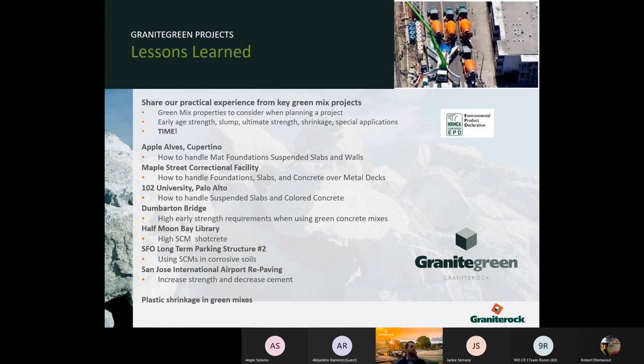Another one similar to the Dumbarton Bridge is the SFO long-term parking structure. The engineer had a very conservative spec, meaning more strength required than really needed. However, they also wanted to incorporate SCMs. To meet that, Graniterock had to incorporate SCMs, but to achieve the early strength, like the Dumbarton Bridge, we had to add the same amount of cement as if we didn't add in any of the SCMs. So it's good to ask for the use of SCMs, but sometimes if you can delay the set, you can decrease the cement, or if you can design with a less conservative approach, you can decrease the cement as well.